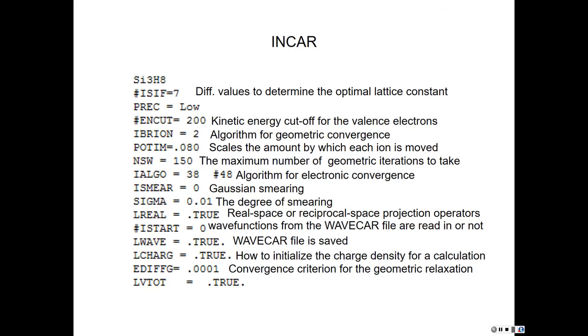And here, as I was explaining, these are the different parameters. This NSW is the maximum number of geometric iterations to take. ISMEAR is Gaussian smearing, and sigma is the degree of smearing, and LREAL means whether we will choose real space or reciprocal space.